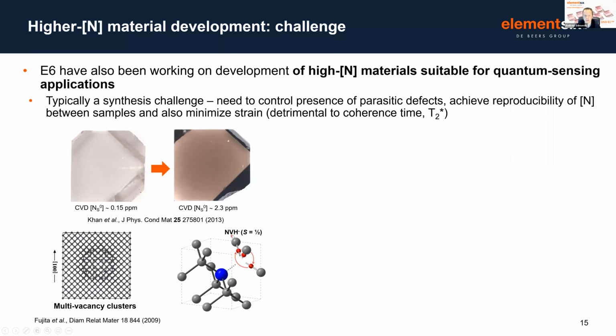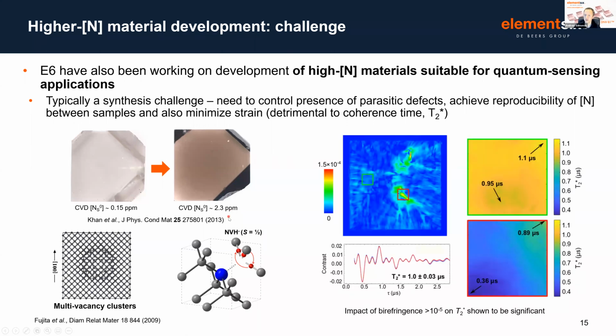Now, NVH minus, for example, is also paramagnetic. So very clearly the presence of these sort of defects can have a dephasing effect on the diamond and reduce the performance of the material. The other obvious point is that if a material becomes less optically transmissive, we're going to start absorbing some of the laser light that we're using to excite the luminescence, or potentially absorb the luminescence generated within the bulk of the diamond sample itself. So this is really critical to minimize if we can. We want to increase the amount of nitrogen in the material, but not at the expense of these sort of properties. And then I mentioned strain.